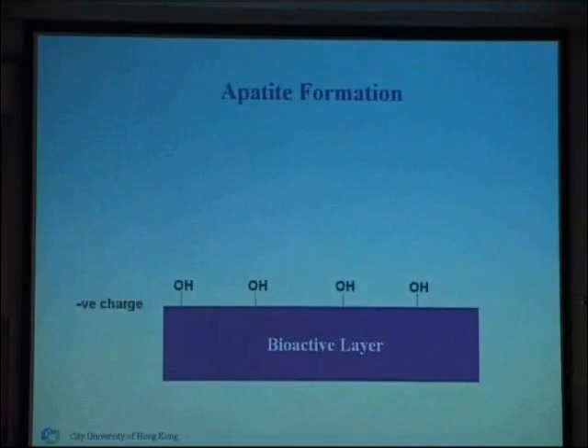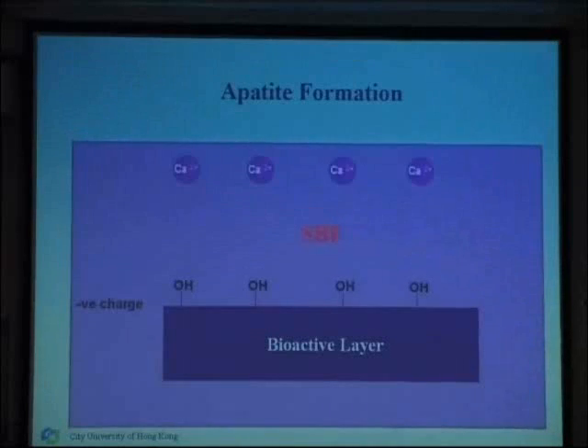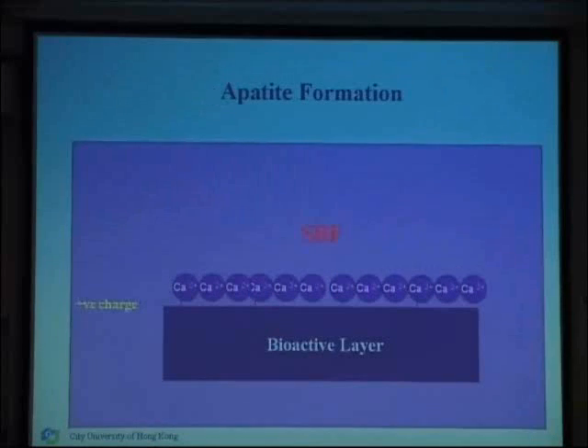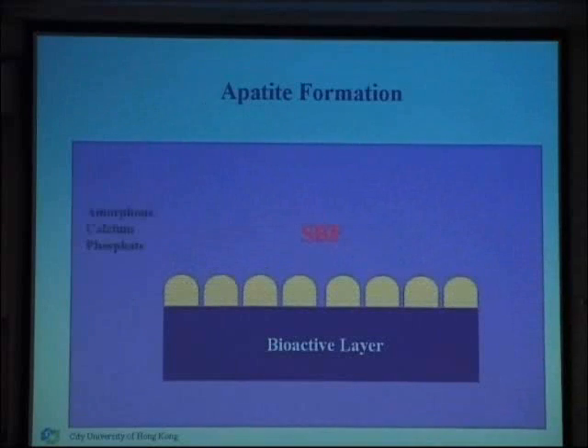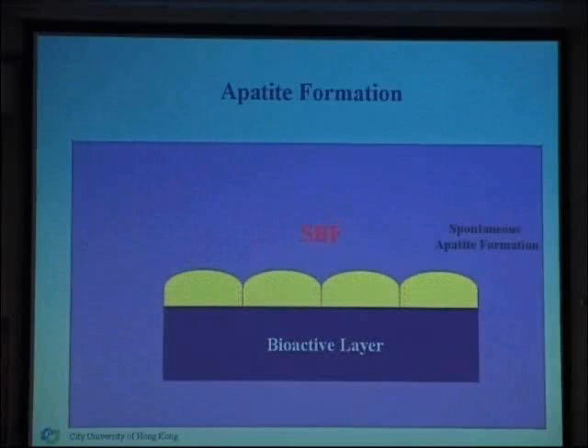Interesting. How does it work? Well, if you have normal silicon, it doesn't work. What we have done is we've implanted hydrogen. So that means the surface is now hydrogenated. And then in water, this becomes O-, the hydrogen goes away. And then in the body fluid, you have calcium ions. They are attracted and become positively charged. And then the phosphate comes on, and you get calcium phosphate, and this continues and continues. That's why we have calcium rich at the interface, and then becoming less rich, and becoming calcium phosphate. Beautiful.